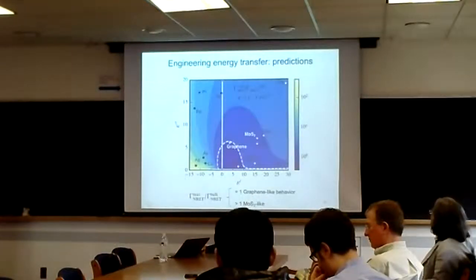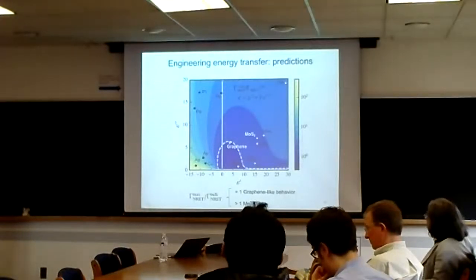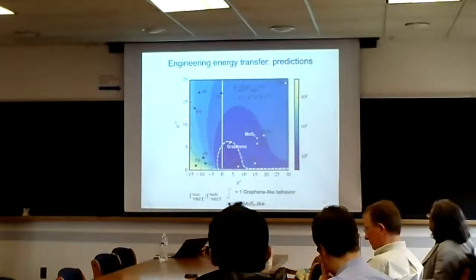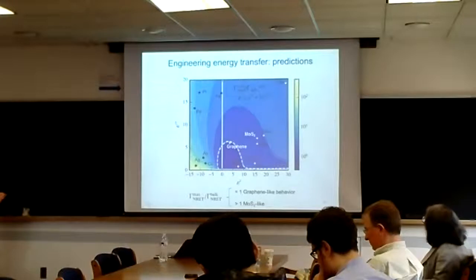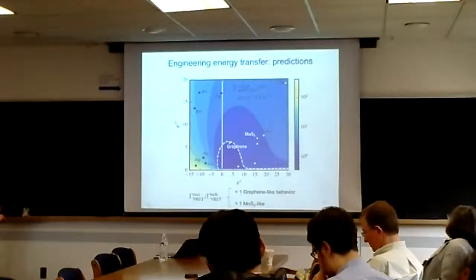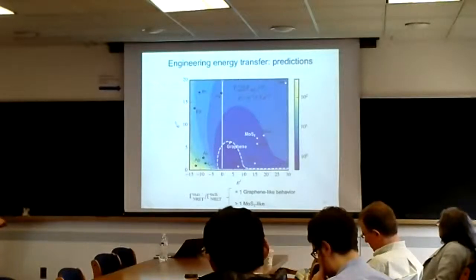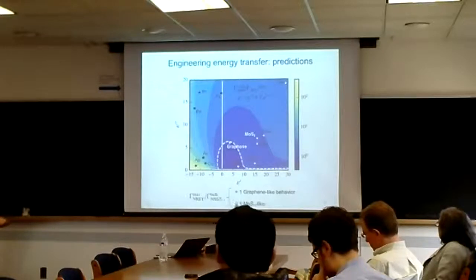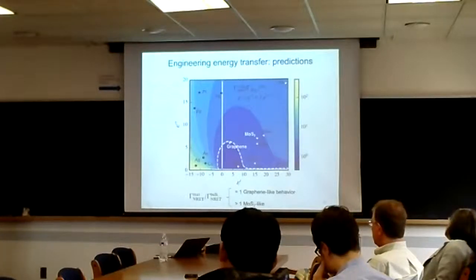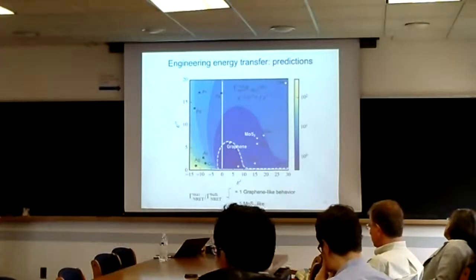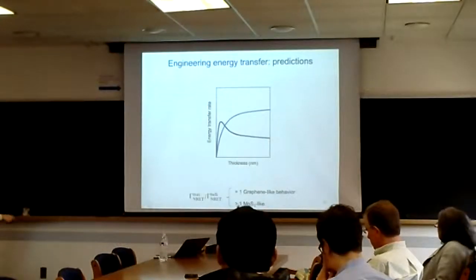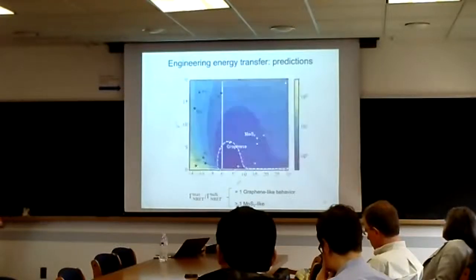So just to cut to the chase here, if you want to make your new solar cell or some stack of materials for your application, we don't have one parameter that just changes and tells you which way it behaves. But what we did do is plot the analytical function. We have a real part of the dielectric function here, imaginary part here, and the colors tell you the maximum decay rate over the bulk decay. So if this number is equal to 1, it behaves like graphene. The more layers you add, the more efficient the energy transfer is. And if it's greater than 1, it's more like MoS2. So this would be like MoS2, this is like graphene, and this metric would be equal to 1 or greater than 1.